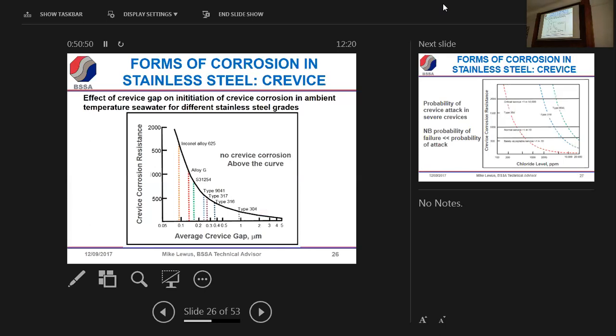We also know what was married with this curve is as we go up here, we go from something like 2 times the chloride concentration in seawater to about 10 or more times. So you know it's virtually impossible to find crevice corrosion or pitting in these kind of alloys, because it's just extremely unlikely to get the conditions that are going to give rise to it.